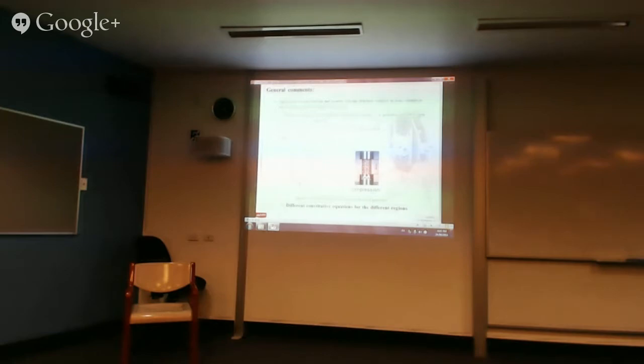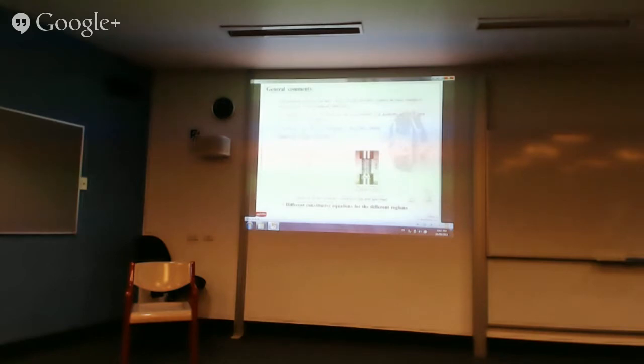Why this is interesting? If you think about one of these previous pictures where a hollow profile was stiffened with the cellular material, a possible application could be a crash absorber. Well, for a crash absorber, what is important is basically the energy that we can absorb. So the energy is the area under the stress strain diagram. And the stress should not be too high, because if you think about a car crash, it would mean the accelerations are not too high for the passenger. Okay? So there are different ways to absorb energy. You could have basically a very stiff material, but this would mean it deforms not much and the accelerations would be very high. Or rather some kind of soft material where we have this plateau region where the stresses are not too high, but the same energy can be absorbed because of the length of this plateau and the accelerations would be much lower in the case of an accident.